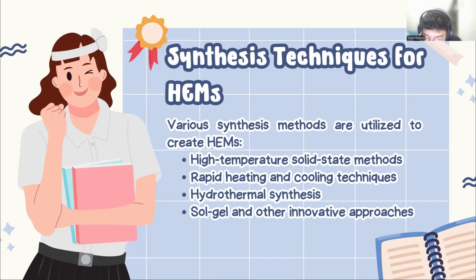Therefore, various synthesis methods are employed to safely and effectively form high heating and cooling gradients during the sintering process, such as laser irradiation, spark plasma sintering, and heating by arc, microwave, or oxygen plasma. To achieve reaction pathways similar to solid state sintering, a method of locally heating small amounts of samples with high power density has been proposed. The Wang team utilized carbon nanotubes and metal acetylacetonates for microwave synthesis of HEM.